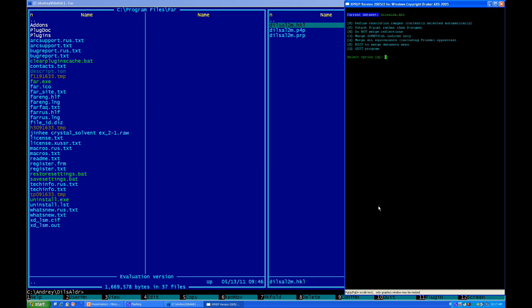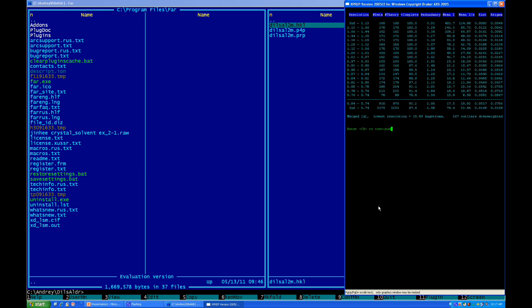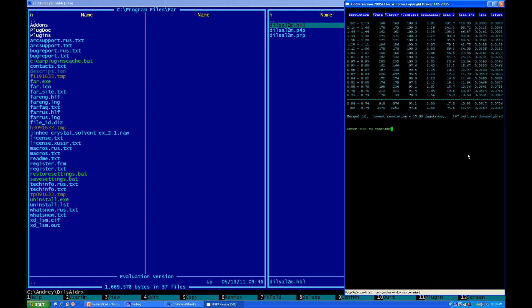What we're doing next, it's reviewing the statistics. You can see that what you need to look at, how much in percent you have your data. Pretty much you have, majority of the time, 100%. So, we collect our data quite good. Redundancy, it's about 2,3, so it's not that bad for monoclinic crystals. We can promptly solve our crystal structure without any problem.